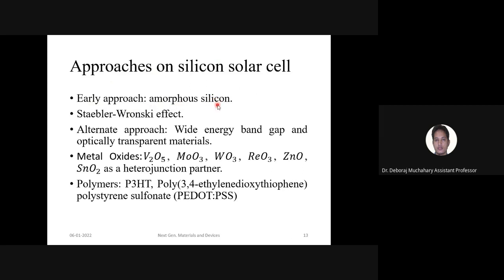So amorphous silicon was the material that people used like 5-6 years back, but the serious problem here is the Staebler-Wronski effect. The Staebler-Wronski effect is that when you expose the device to light for a long duration, the device performance will be degraded, because the defect density inside the amorphous silicon will be boosted by the light exposure. So this is called light degradation, and it is named after Staebler-Wronski.